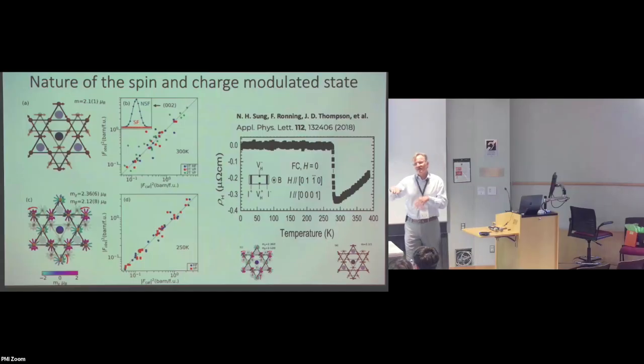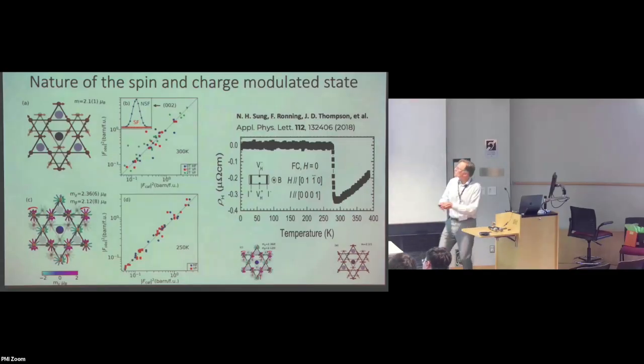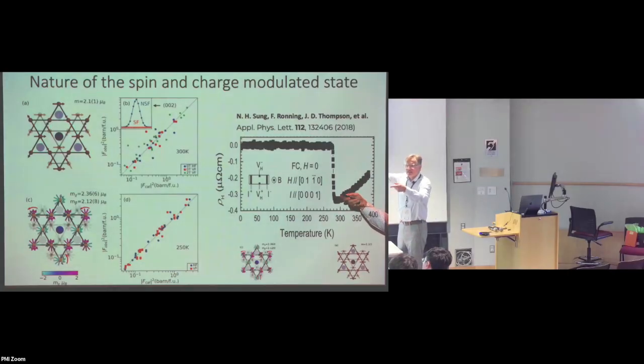And so that little remnant moment, you might say, well, if I calculate the B field induced by that, that will definitely not be enough to cause a significant Hall response. However, because of the symmetry that it carries, the fact that time reversal symmetry is now causing the flipping of this entire structure, that ensures that there will be the possibility of a split electronic band structure, and then you get all of the Weyl physics and everything comes out of it. So that's the story basically. And so once we begin to rotate this from layer to layer, then the orientation of this fictitious magnetic moment, which is so important for the transport properties, is now scrambled, and I really lose the macroscopic effect.